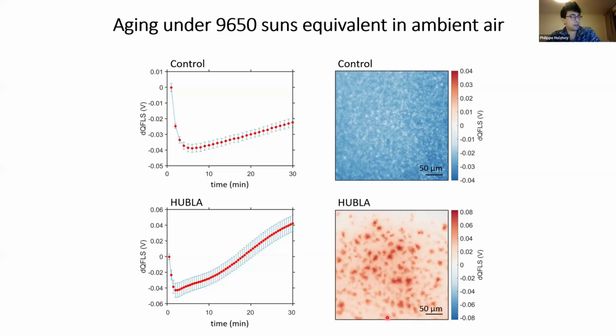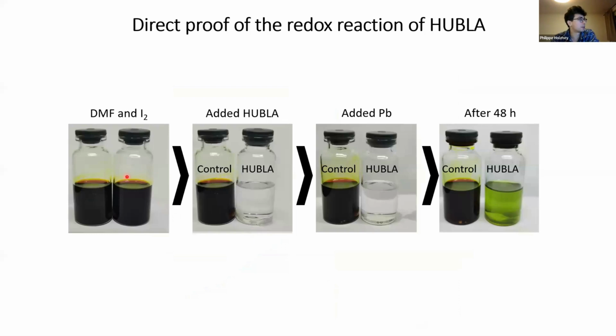Yeah, and another experiment we have done to prove the dynamic passivation of HUBLA is we have a DMF solution with iodine. So it's black. And then we add the HUBLA to one of the vials and to the other not. And you see very quickly how the solution is turning clear because it's the redox shuttle again. The iodine is reduced to iodide, it becomes clear over time.